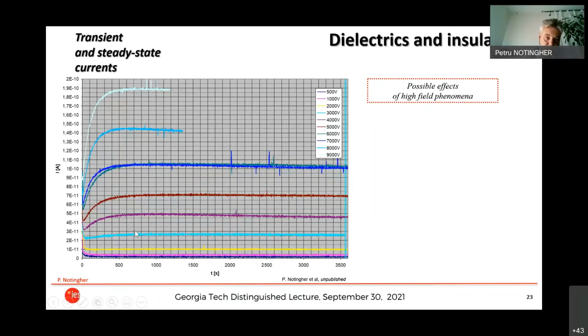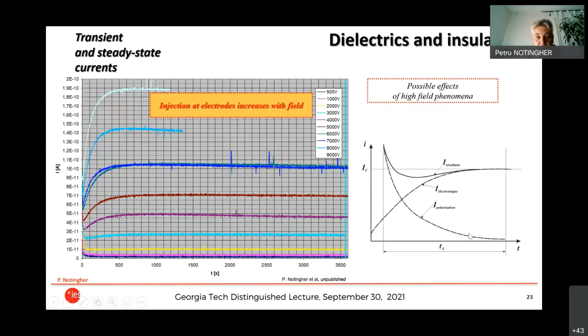And then after 3 kilovolts, the shape of the current changes, and a lot, and this has nothing to do anymore with the absorption current that we showed before. And why does this happen? Because you will inject a lot of charge at the electrodes, and the injection will increase with the field. So you do not fulfill the ohmic conditions anymore. You have, of course, the polarization current, which always stands, but you also have a current which is due to the injection of the charge. And this current will cross the polarization current, will become predominant, and this is why you may encounter this type of measurement. So this means significant charge injection may occur at electrodes under high field and temperature.